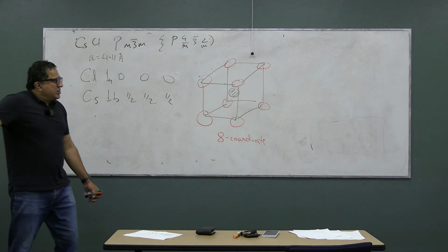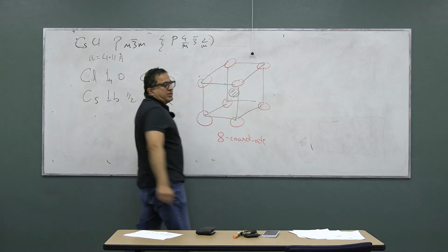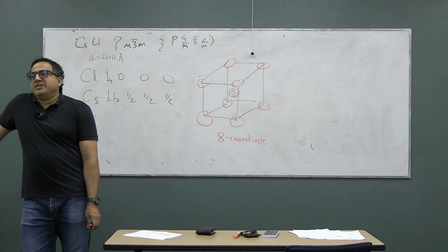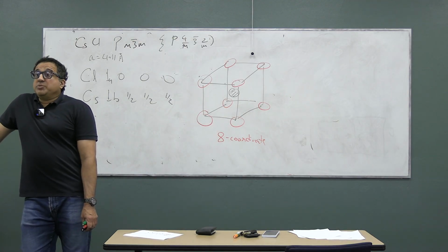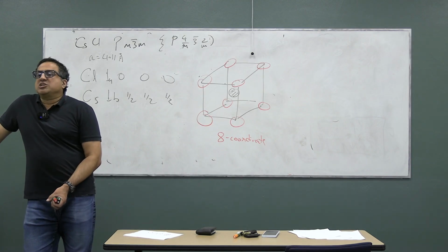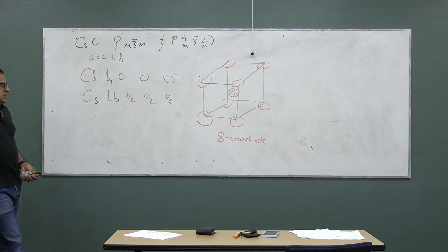Right? And if you look at the next cesium chloride cell, you see that these 4 chlorides form a face that is shared between 2 cells. So the polyhedron is the cube, and these cubes are face sharing. But cesium just has a 1+ charge, so it says, I'm fine, I don't mind face sharing because the charge is low.